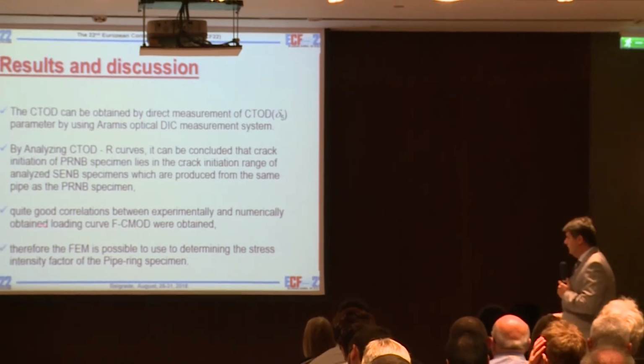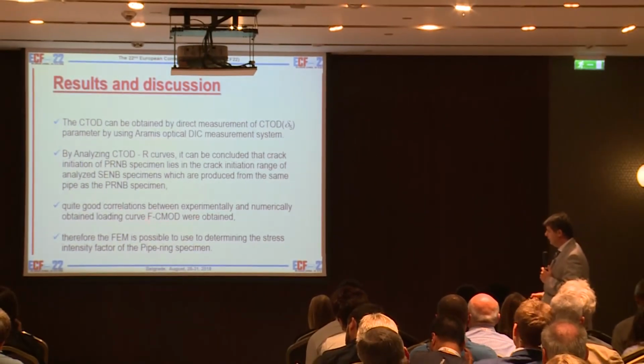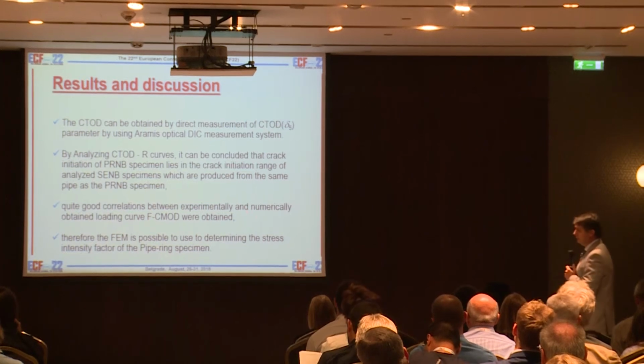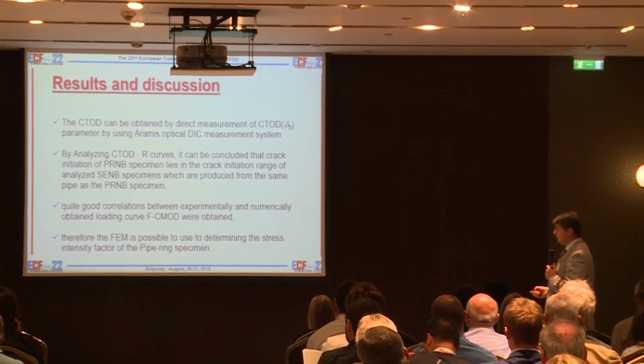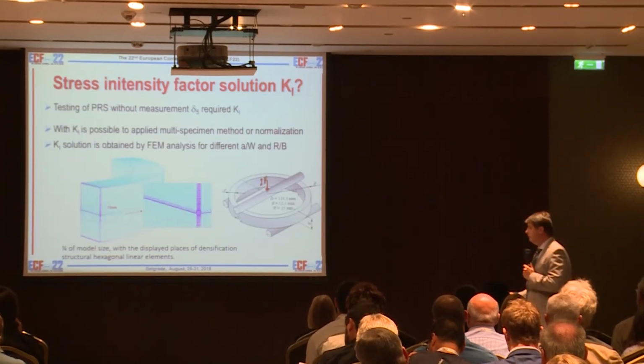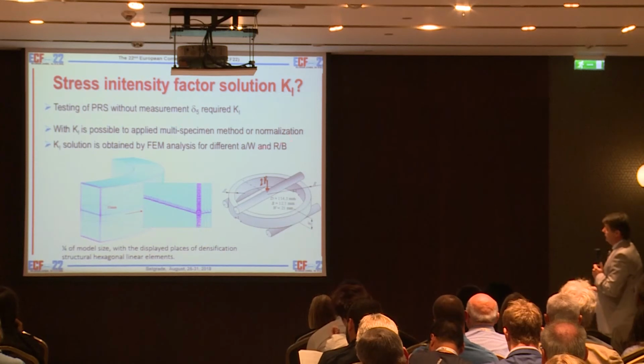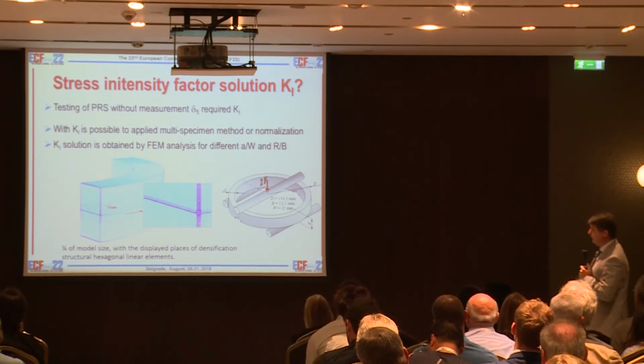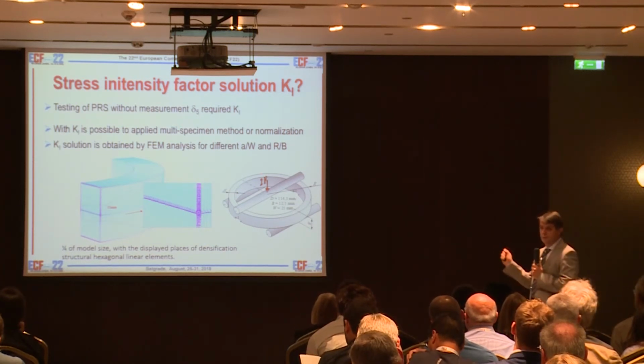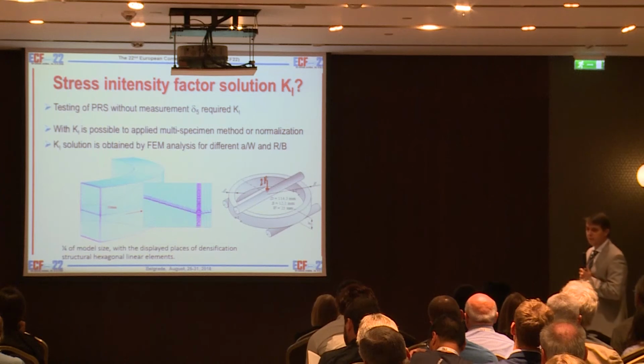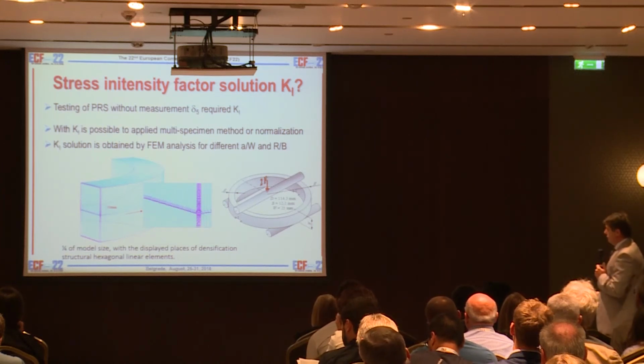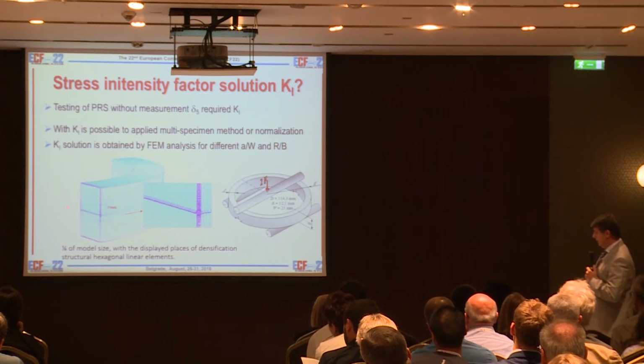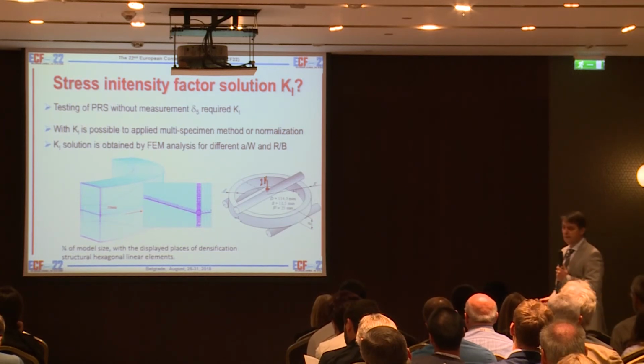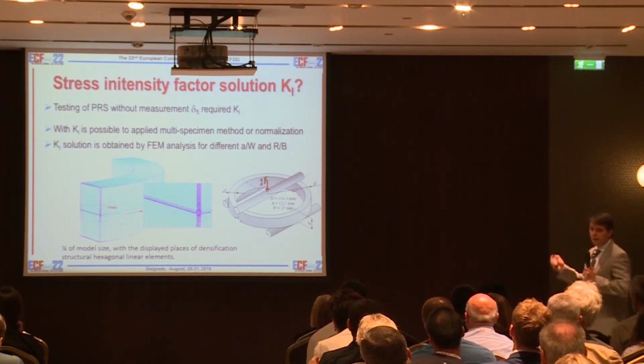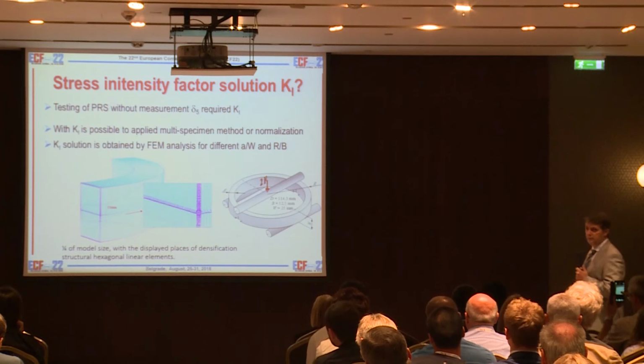So this is also we got a quite good relation between experimental and numerical results. Therefore, we can actually try to now determine stress intensity factor, because this is what we need in the practice, so that engineers can put in some parameters and easily calculate. So we did this. Of course, now we use the straight line of the graph because it's universal, so everybody can repeat and check.